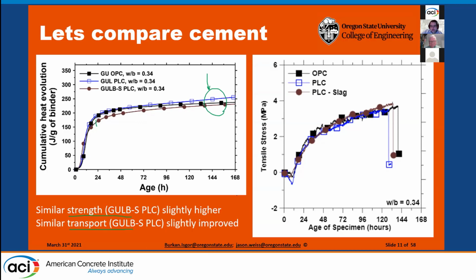Then there was a question about shrinkage, and we've measured the autogenous shrinkage, and it's very similar. Here you can actually see the shrinkage cracking stresses. Now, this is a very high-paste system to try to drive the cracking, because there was a lot of concern with the finer limestone powders. Would these materials be more susceptible to cracking? What you see is they behave almost identical to the OPC system. So there's really not a huge difference, and we can get into all of the reasons why that's the case, even though it's a finer system. It has to do with the fact that it's really the limestone that's finer in that system.